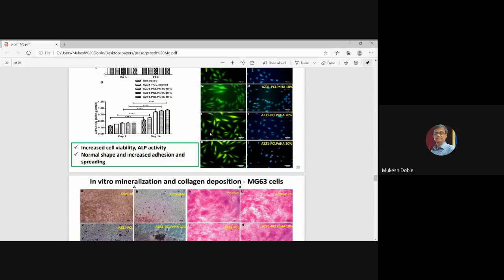Okay, normal shape. You can see the shape of the MG63 cells. Increased adhesion and spreading. You can see that they are increased cell viability and very good ALP activity, alkaline phosphatase, because alkaline phosphatase tells you the mineralization of the cells. Ultimately, when the bone cells start mineralizing, that means they are growing well. So the coated surfaces, you can see very high mineralization after 28 days. Initially, they are almost the same, but higher the HA, higher is the mineralization, as you can see in this graph.